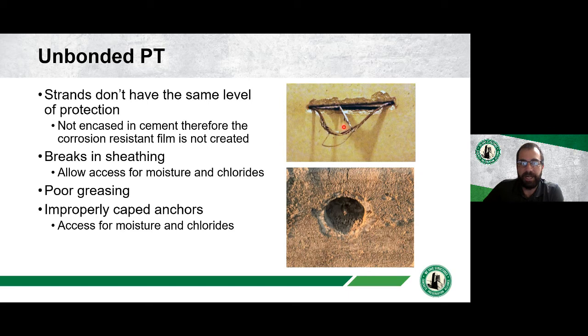So these are strands in plastic sheaths that have grease inside to protect them from corrosion. However, breaks in the sheath or not properly done anchorages allow water or chlorides to get into those strands and can cause corrosion of that strand and eventual failure like this.